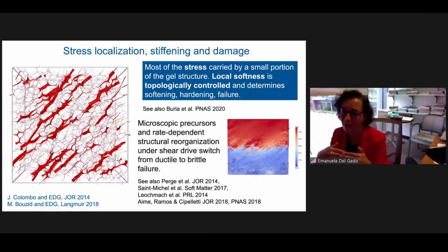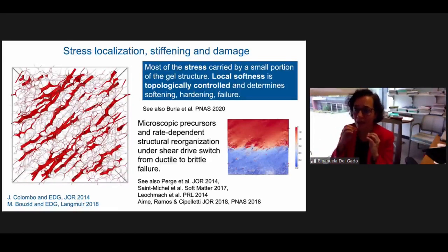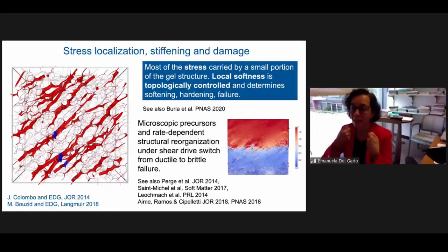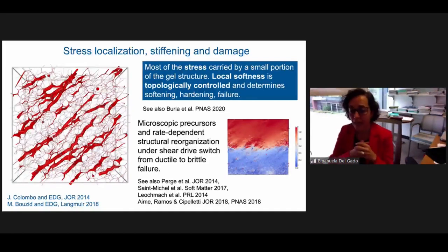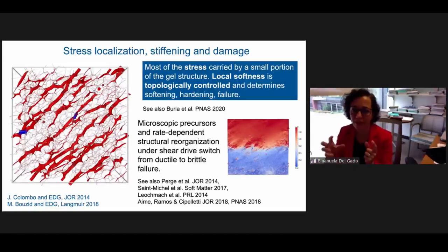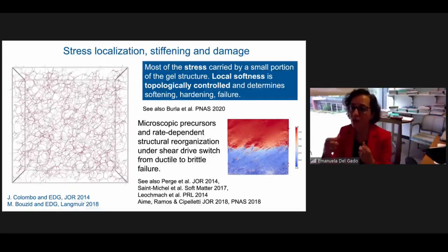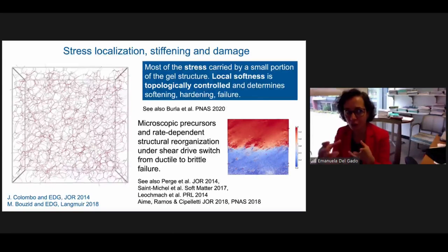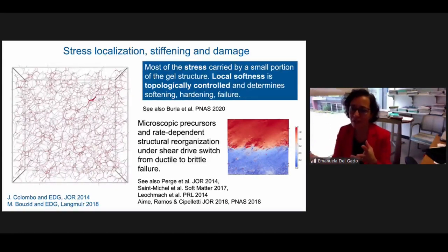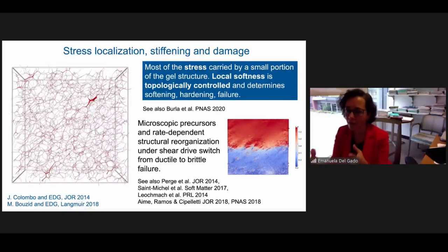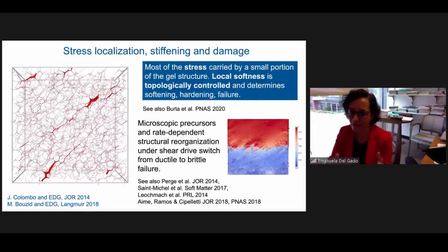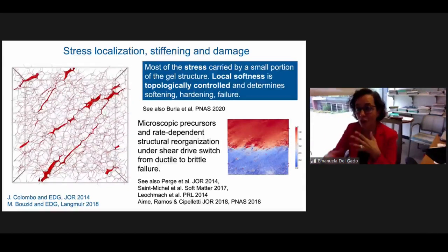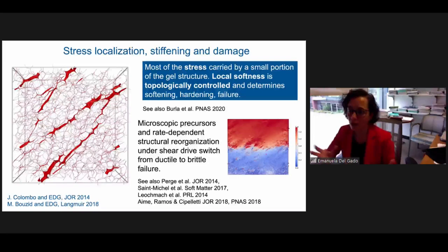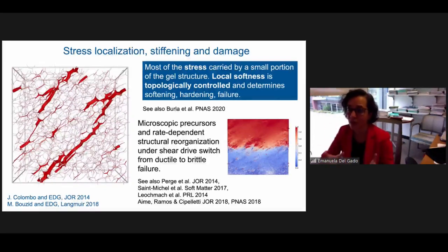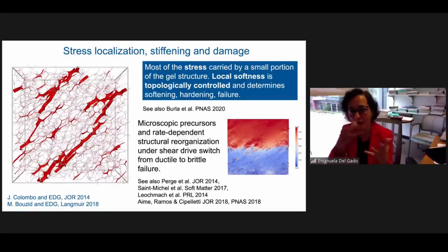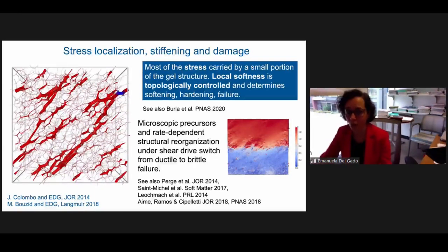So you can see that from the beginning, there is a very small portion of the material where this tension tends to accumulate. And what is interesting is that this region where tensions accumulate is determined by the topology of the system. So there is a local softness, or a local stiffness, in the material that is determined by the way the network is spatially organized, and the connectivity of the network is spatially organized through how the topology is organized.